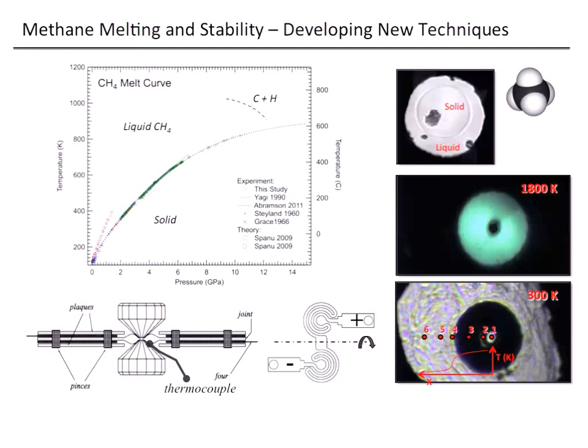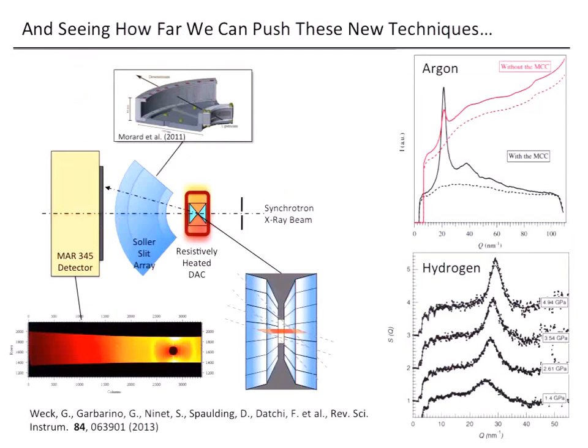You want to both confine the sample, as we're trying to do with these little donuts, but also create a uniform temperature distribution. The other advantage is that we can take this to the synchrotron and we can look at properties like liquid structure factor.